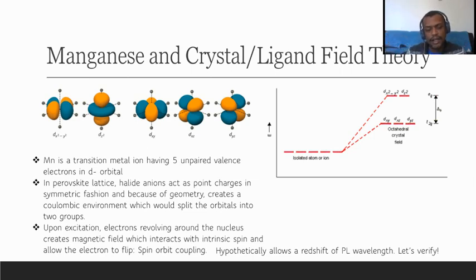So they will have a higher energy than the other ones, where the lobes are not directly on the axes where these point charges will be. So these first two will have a higher energy than the three other ones, and this is called crystal field theory or crystal field splitting. So these 5 electrons in the d orbital will be separated into two groups, where two of them would have higher energy and three of them would be a bit lower, but overall all of them will have a higher energy than when the manganese ion is in vacuum. So that's what you can see in the top right image.